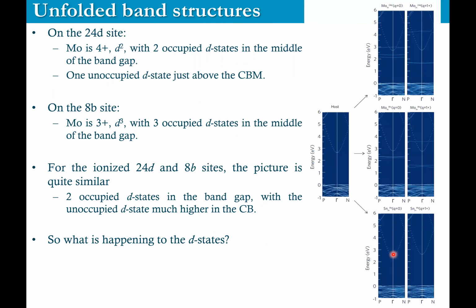So what we can do is we put our defect in a supercell, and we've calculated the effect of this, and we can now unfold band structures to try and understand where these defect states fit within the band gap of the systems that we're interested in. So on the 24D site, molybdenum appears to be molybdenum 4+. It's formally D2, so 2 occupied D states in the middle of the band gap, and 1 unoccupied D state at the bottom of the conduction band, or just above it.